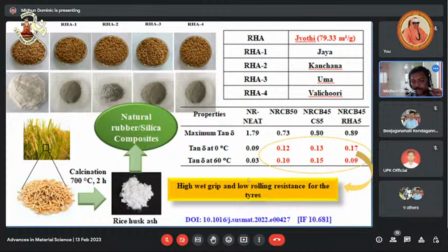There is a parameter that can determine this rolling resistance, that is tan delta. This can be obtained from dynamic mechanical analysis, DMA studies. Tan delta is called loss tangent. It is nothing but the ratio of loss modulus to storage modulus. We have to remember one thing: tan delta at 60 degrees Celsius is a measure of rolling resistance. The lower the value of tan delta at 60 degrees Celsius, the lower will be the rolling resistance, the higher will be the fuel saving efficiency, and the lower will be the carbon emission. So this is the concept; we have to reduce the parameter tan delta at 60 degrees Celsius.